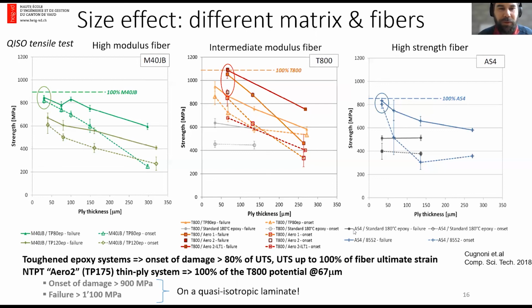It was actually the same idea as we have for the pull-out control, but we are using fragmentation of the fibers, and they were using a cutting process. But there's a lot to be done by tailoring damage, and I think that's the future. Introducing controlled defects to tailor damage to have exactly the linear elastic and then non-linear dissipative regime that you want. I think this is a hot topic.